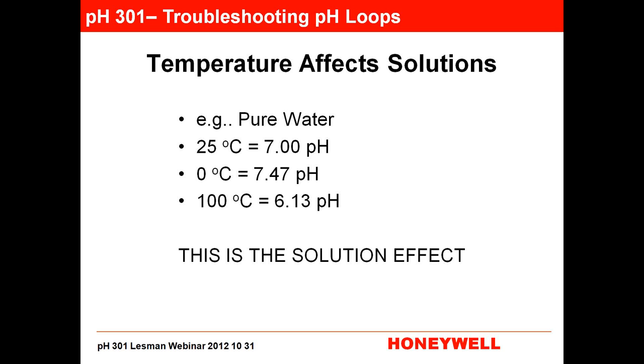The temperature compensator doesn't know anything about the chemistry of your solution. It only knows that the temperature has changed. So at 100 degrees C, it's going to be putting out about 70 millivolts per pH unit, approximately. And it will be compensating for 100 degrees C in the Nernst equation. But it can't compensate for what's happening chemically in your solution, in this case, pure water.